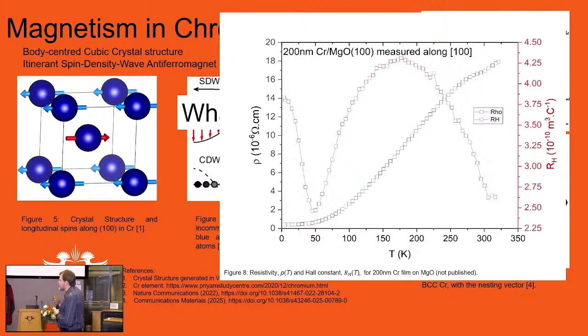The one in red is a Hall measurement, a Hall constant measurement. This tells us something about the charge carriers, the number of them on these Fermi surfaces. It gives you some idea. Again, you come out of the paramagnetic state, random. You've got condensation, but now you get left behind with this positive character in the charges. From here, of course, we can always calculate how quickly these charges move, on the surfaces or through the surfaces. Of course, there's another anomaly here. This has got nothing to do with the magnetism. This is known as Umklapp scattering that you see in pure chromium. We don't see it in other of the alloys.